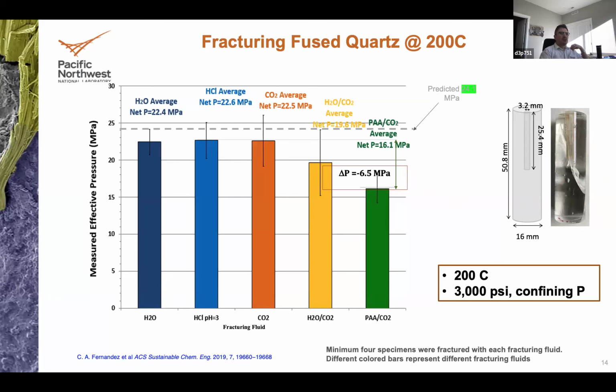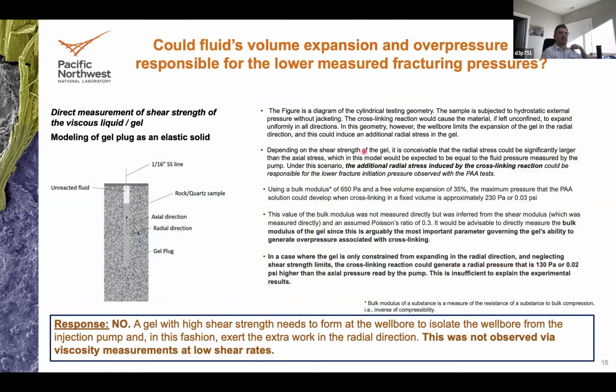And, pardon, all this is just copy and paste from the paper, but what we thought is maybe there's a shell that is being formed. I forgot to say that for the polymer solution, and the water without the polymer, we add 200 microliters, so a volume similar to the wellbore volume. And then we swap the pumps, and we add through a T. So basically there is no PAA or polymer solution or water outside the wellbore. And then we add CO2, and we start at constant flow rate, increasing the pressure.